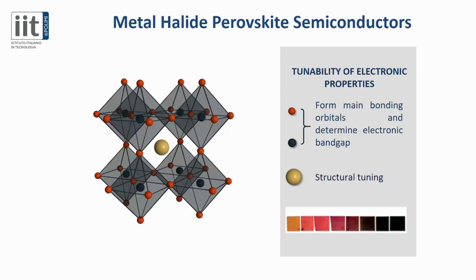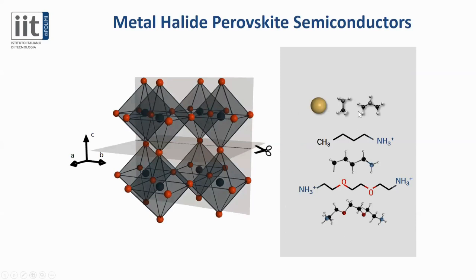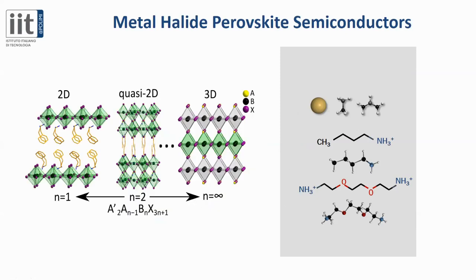So the first two mainly form the main bonding orbitals. So in a first approximation, they determine the electronic band gap of the semiconductor, which can be tuned by changing the chemical composition. What you can see here on the bottom is a thin film made of perovskite with different band gaps, while the cation in the middle is mainly there for structural tuning. You can change the nature of the cation, its size, the functional group, and change the structure of the metal halide perovskite, for example moving from 3D to quasi-2D, 2D, and going to actually 0D semiconductors.